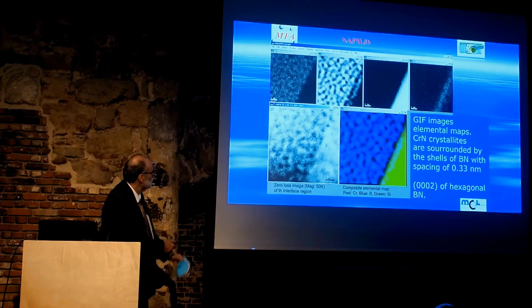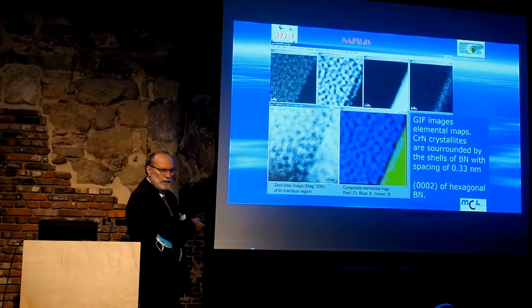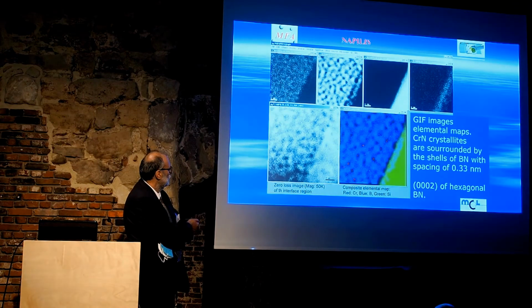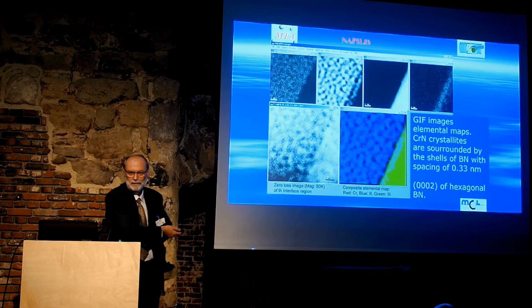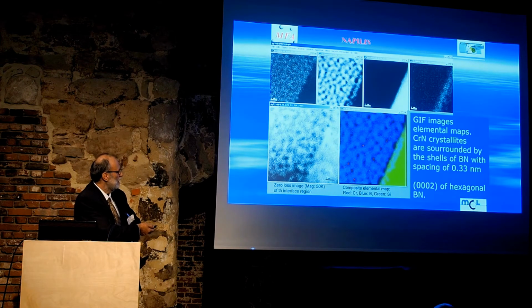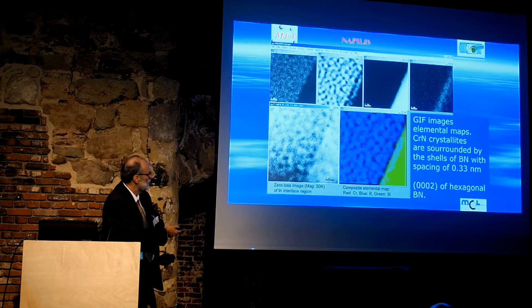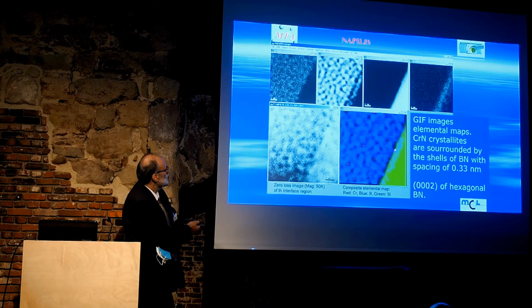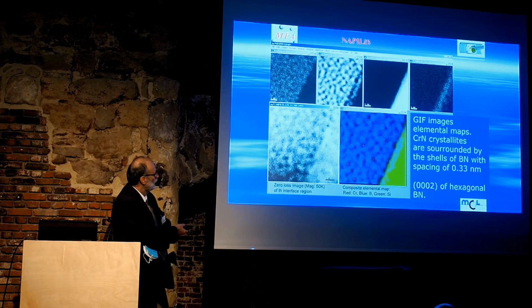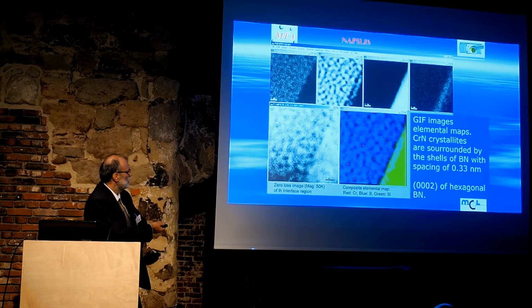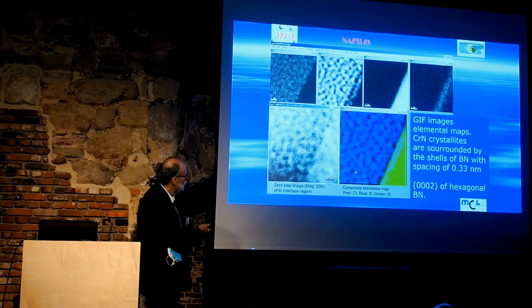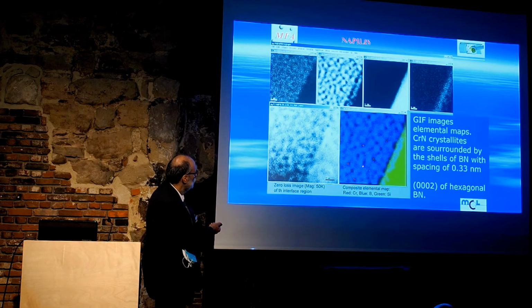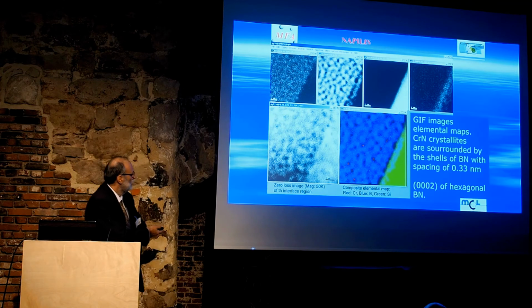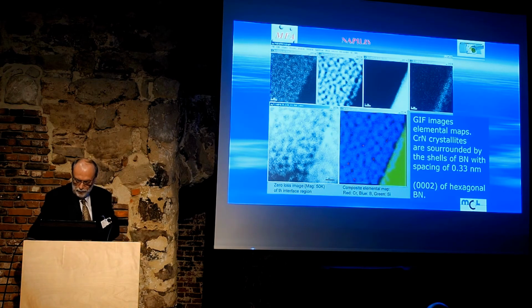This is an image which we took on an older microscope of ours, and we demonstrated the elemental mapping at the nanometer scale based on electron energy loss images. In those days we had a car industry project, a European project, with Mahle, a big German player in the car industry, with 150,000 employees. And here we could determine the chromium nitride and boron nitride functional coating.